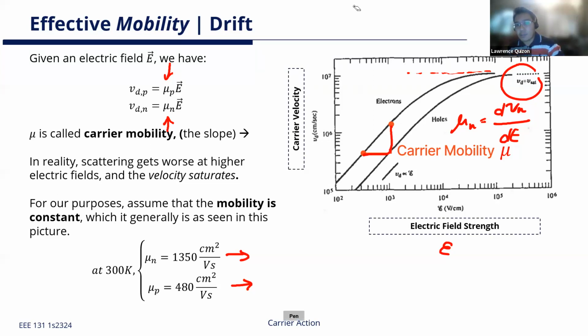So then, what saturation means is that it starts off fairly constant and then it drops hard to zero, no? So pag ganun siya, ang carrier mobility, no? With respect to electric field. So that's one thing I wanted to point out. But for the purposes of this course, we're going to assume that mobility is quite constant, no? Hindi tayo nagsasaturate. Because an electric field strength of magnitude 10 to the 4 and above is actually quite a lot, no? That's power electronics level, not integrated circuits level.